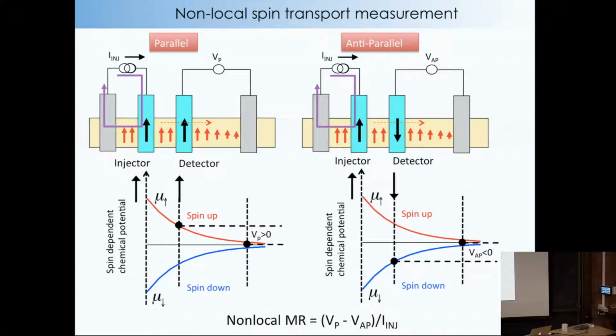So over here at the injector, you have a spin up chemical potential, a spin down chemical potential. And as you go to the right, because you have spin flip scattering, you start depolarizing the spins as you go to the right. And so the overall spin density is going to decay, okay? And the way the detection works is, if you have a spin-up detector, it's going to measure the local voltage, this mu up of the spin-up. Whereas if your detector has opposite spin polarization from your injector, then you're going to measure the spin down chemical potential, right? So this is how the spin polarization gets converted into a voltage that we measure. And there's a whole bunch of background signals.